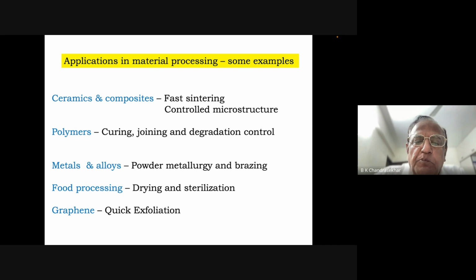If you put a sheet of copper or steel or anything like that into a microwave oven, it will reflect. But if you make it into a powder and press it into a pellet, typically the porosity will still be of the order of 25, 30, 40%. And when the porosity is present, the microwaves do get absorbed and heat the material, and then you can sinter that material. So therefore metals and alloys can also be used with microwave.